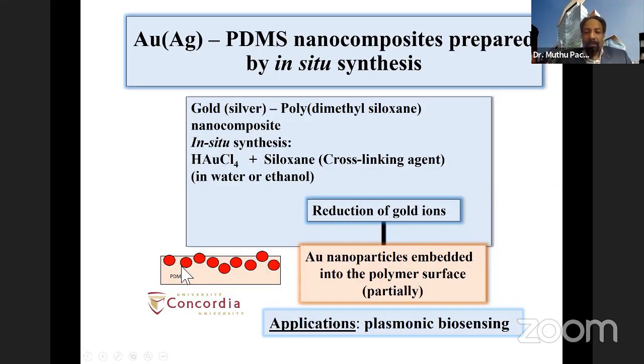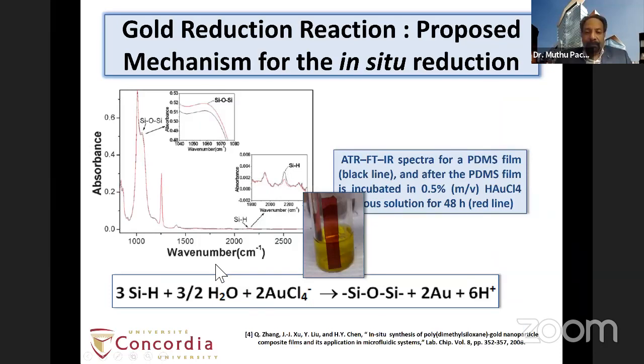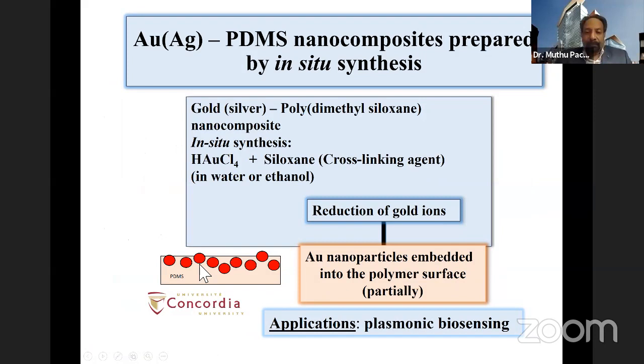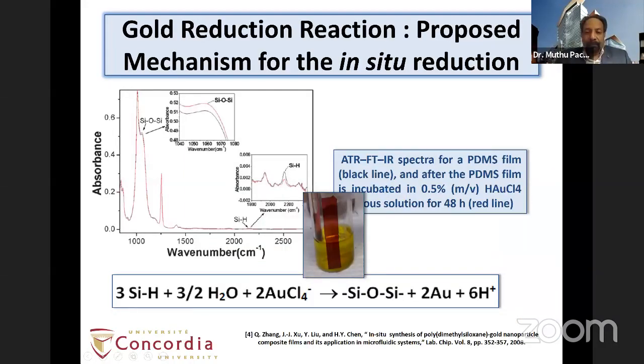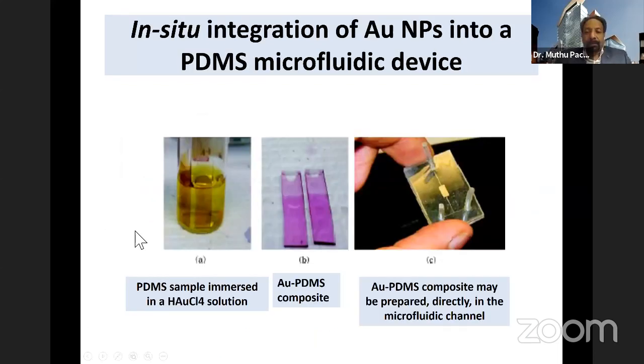So you can see here, we can do the in situ synthesis of nanoparticles, and then you can make composites of nanoparticles, as you see here, and the PDMS substrate in this case, but you can also do other material which basically reacts with this gold precursor to create nanoparticles. So you can in situ synthesize a PDMS-gold composite in this case. You can do it on a substrate, or you can do it on a microfluidic base. It's whatever, depending upon one's interest. One can do this in situ PDMS composite.